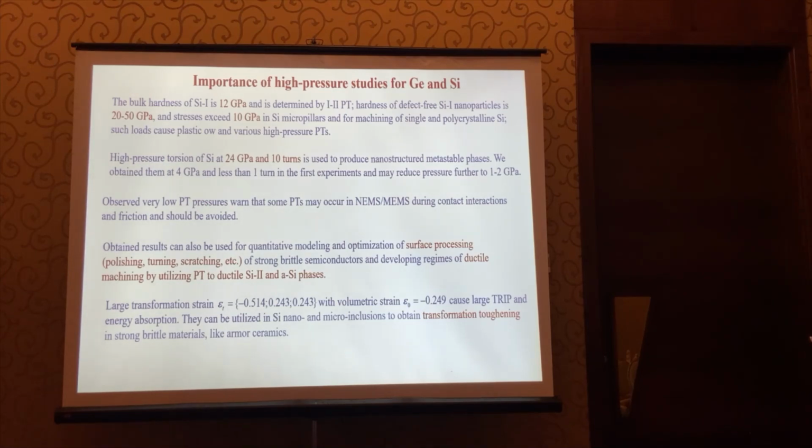Also, we observed very low pressure for phase transformations. This warns that some phase transition in NEMS, MEMS may occur during contact friction, which is probably undesirable. So this should be checked and taken care of. Also, our results can be used for quantitative modeling and optimization of different surface processing and for semiconductors, and also for developing regimes of ductile machining by utilizing as plasticity mechanism, phase transition to ductile silicon 2 and amorphous phases.